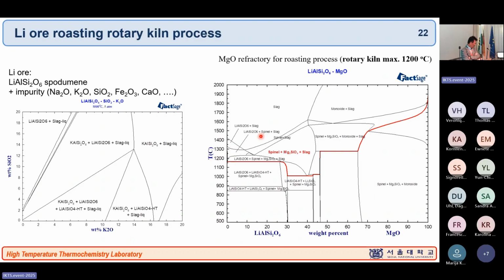And one of my sponsors stupidly took the MgO without my advice. And then they said that the entire rotary kiln refractory was making a chemical reaction with the lithium ore. So we did the calculation for them. Here, this is spodumene, LiAlSi2O6, and this is MgO. And you have never seen this kind of phase diagram before. But here, this red line shows you the minimum temperature for the slag formation. So if you are doing a 1200 degree operation, here you can make a huge amount of liquid slag, which can stick inside your rotary kiln and make more and more damage, and then eventually it fails.